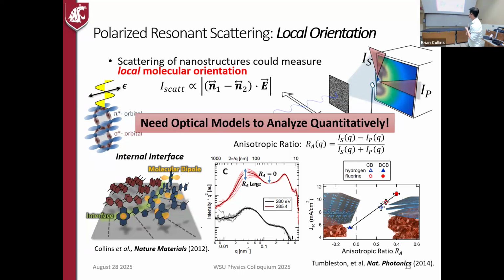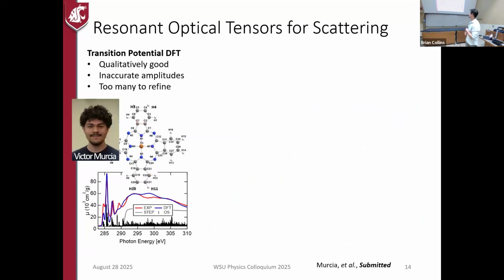And so we need better optical models to do that, though. We just don't have really good optical models. So one of the projects we've done here at WSU with Victor Murcia is look at density functional theory calculations to see if we can develop these optical models. We'll need an optical tensor actually to look at orientation, right? So we used transition potential DFT.